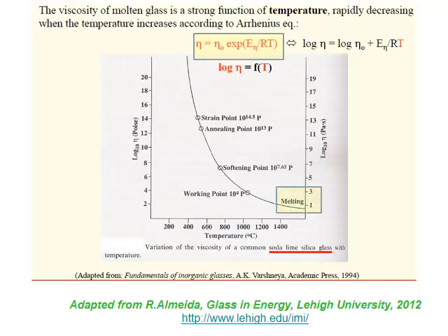These are: the melting or fining point is the temperature at which the viscosity value is around 10^2 poise. At the working point or forming point, the viscosity is 10^4 poise. At the softening temperature, the viscosity is 10^7.65 poise. The annealing point is usually defined as the Tg temperature, that is, the viscosity is 10^13 poise. And finally, the strain point, where the viscosity is 10^14.5 poise.